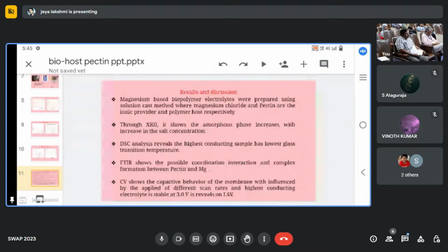application. Then, conclusions. For the biopolymer electrolyte, I take the magnesium salt as the ionic provider and the pectin as the biopolymer. From XRD, I confirm the amorphous nature of the biopolymer electrolyte film. DSC analysis reveals the highest ionic conducting sample and the low glass transition temperature. From FTIR studies, complex interactions between the pectin and Mg are shown, and CV shows the capacitive behavior of the membrane with the applied different scan rates and voltages. And then in LSV, the prepared biopolymer electrolyte is stable up to 3 volts. Thank you.